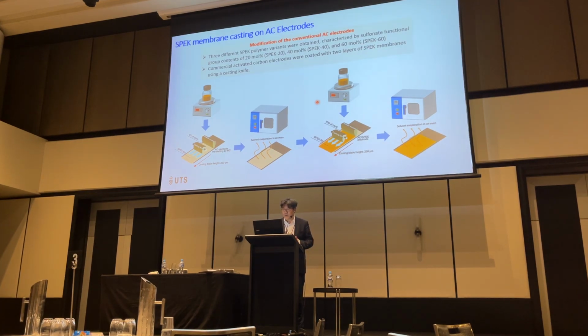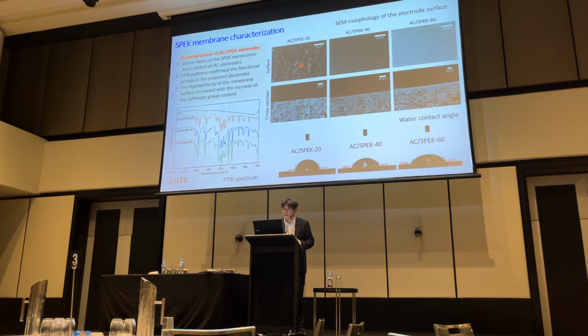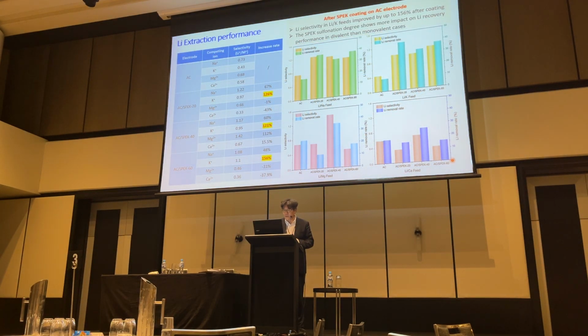So you can see that we use the different SPEEK polymers and coated them with the powder activated carbon. This is 20%, 40%, and 60%. So we coated with them, and then looked at the contact angle. It becomes more hydrophilic from 85 degrees to 63 degrees. So we found the hydrophilicity increases with the higher concentration of sulfonate group. And then we look at the activated carbon only, SPEEK 20%, 40%, 60%.